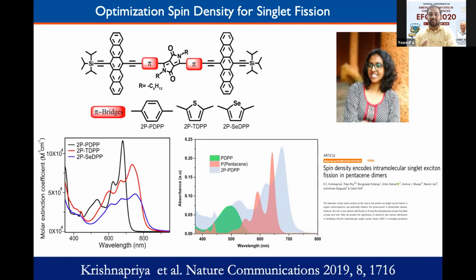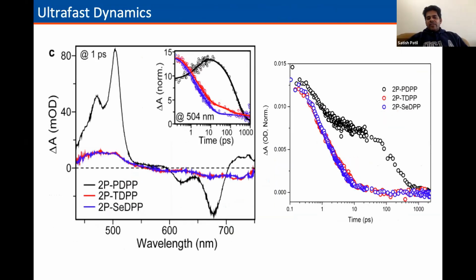Did you find any relation between the excited state dynamics of those molecules? You have shown there one phenyl ring attached and thiophene, so is this pi linking playing any role in the excited state dynamics? Indeed it is changing, because if you look at this plot, the black one is the kinetics we have extracted from ultrafast spectroscopy. The black one shows a signature of a triplet, whereas the blue and the red ones here are thiophene and selenophene. They only generate singlets. They do not generate a triplet signature. So we see there is a big difference in excited state photophysics when we have a phenyl bridge, thiophene and selenophene.